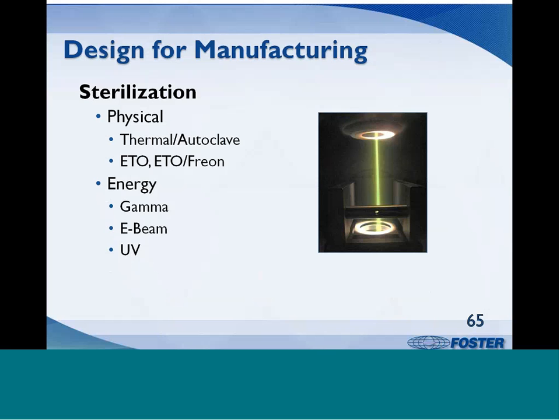Sterilization is something that can have unintended consequences on a resin if not properly compensated for. Nanoclays can enhance the heat distortion temperature of crystalline resins that will be steam sterilized. Crystalline amorphous polymer blends can have improved chemical resistance when exposed to ethylene oxide as over straight crystalline or straight amorphous resins.